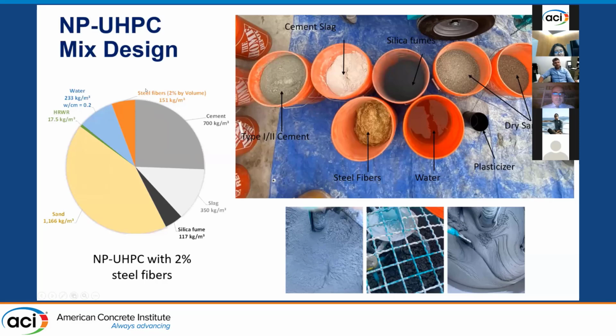And then we used steel fiber, 2% by volume for the basic one, but we also used 1% as well, to show that you can go with less steel fiber for these applications, specifically for the ABC, ETC bridge deck connections. So this is some general information about the mix. This is how you see the close to final state before we finish the material and so on.